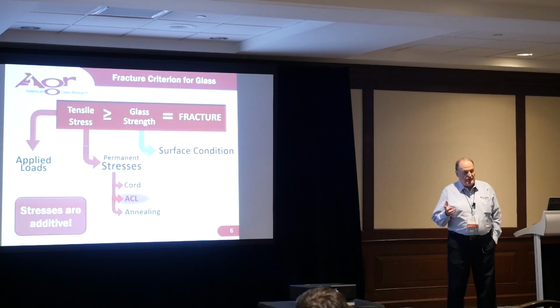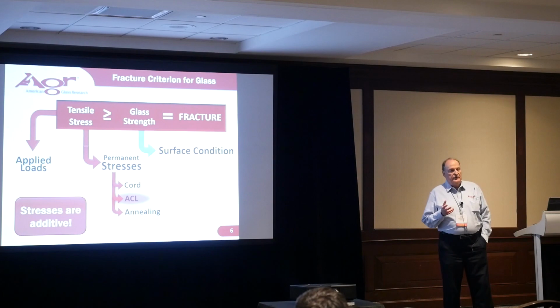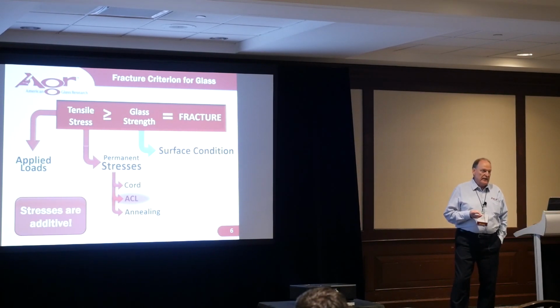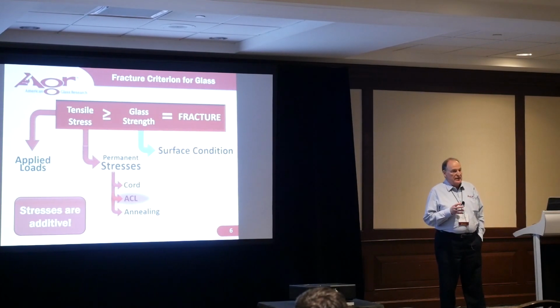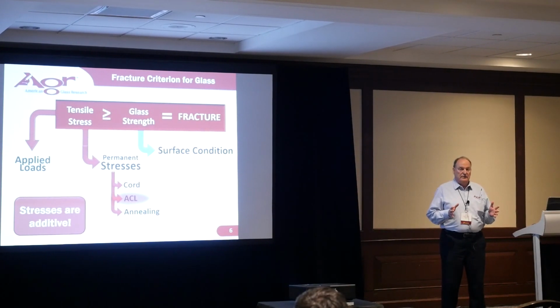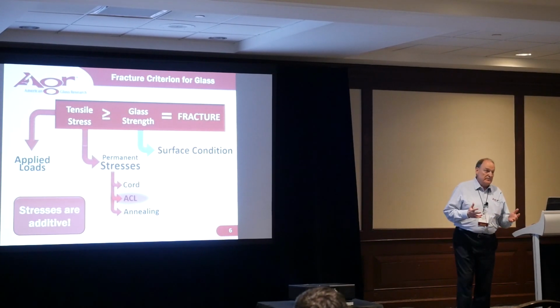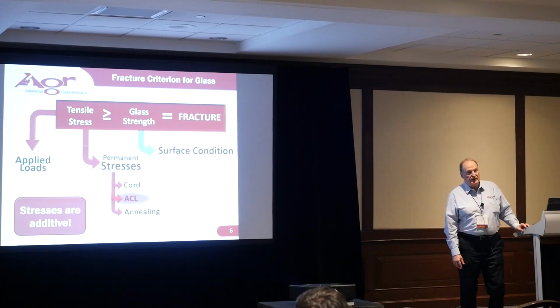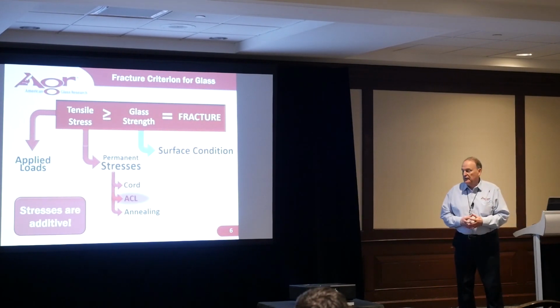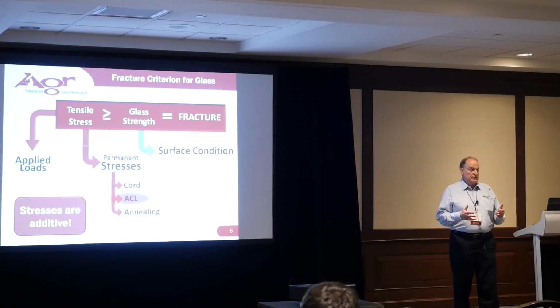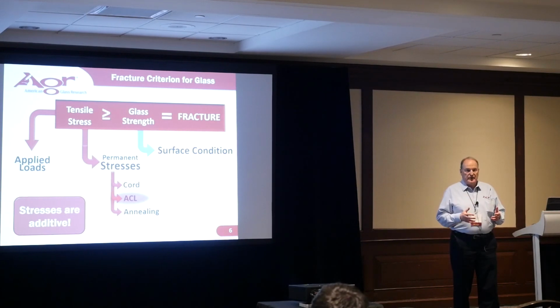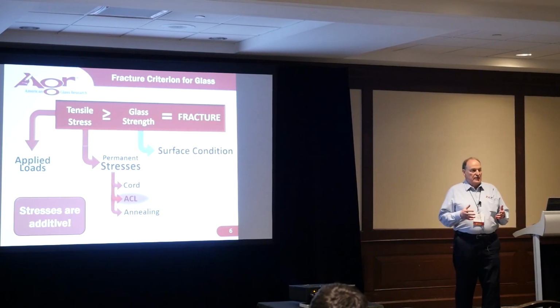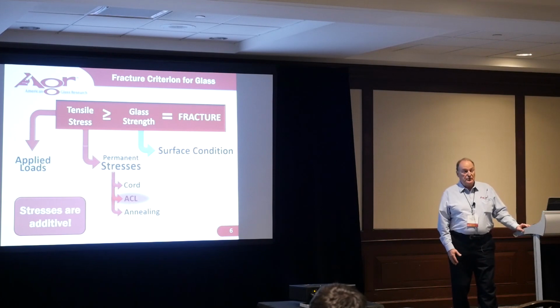Now, the surface condition is very important. If you have what is called a pristine glass surface, or one that is essentially free of any type of flaw, the glass surface strength could easily be in excess of 100,000 psi. Very, very strong material. If, on the other hand, the surface has been abused and contains a flaw that is relatively severe, glass surface strengths might be as low as a few thousand psi. It's a huge, big range.